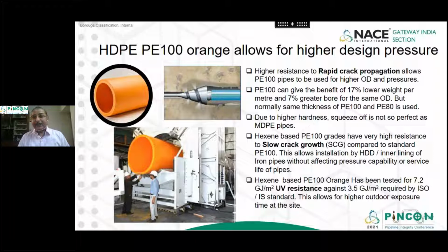You can see that the same MDPE and HDPE, PE80 and PE100 materials for the water industry are used for up to 16 bar and 20 bar pressure pipes. But in the gas industry, they're used for only 4 bar and 7 bar. This limitation is because of rapid crack propagation. If a gas pipe is punctured, the crack may propagate instantaneously to a very long distance because gas is a compressible fluid. Therefore, the rapid crack propagation property has to be measured and it has to be kept within a limit so that it doesn't propagate indefinitely.